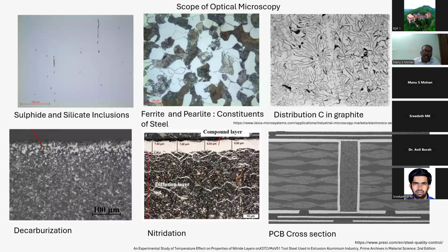PCB basically consists of copper layer, dielectric, pre-preg, solder mask, so many things. There's basically an organic part and a metal part. So they want to assess the thickness, whether there's any erosion, delamination - for that also optical microscopy is used. The side you see here is basically the glass composite, and then you see the copper foil.